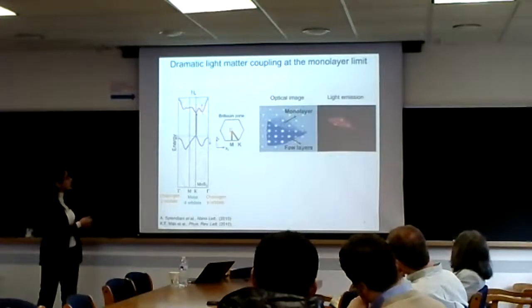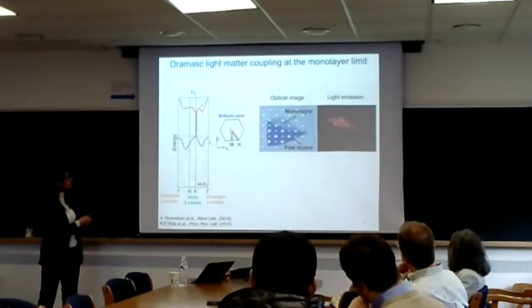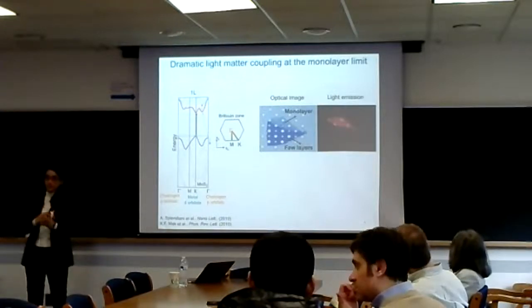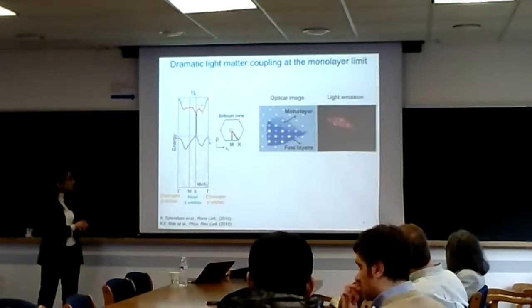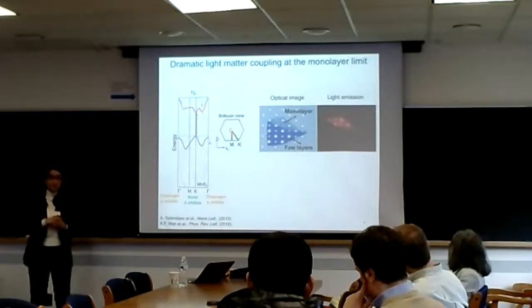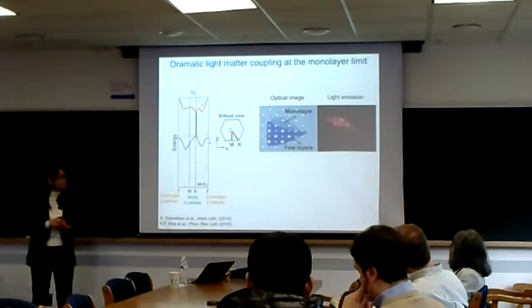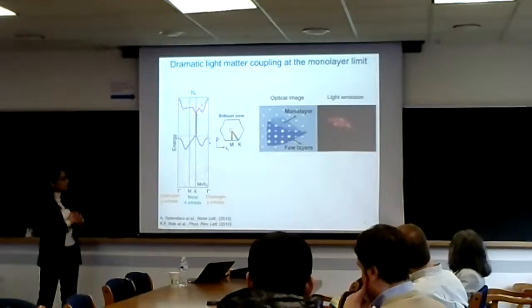Because of this. So you have a monolayer and a few layers sitting on a substrate with holes, and if you were to excite these layers, you see that there's much stronger light emission coming from the single layers than few layers. And already here you can see the sample that's sitting on top of the holes emits brighter light, so it's sort of more sensitive to the environment, and this sort of foreshadows some of the things that I'm going to be talking about today.